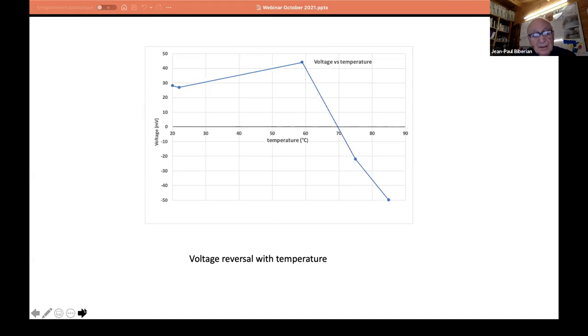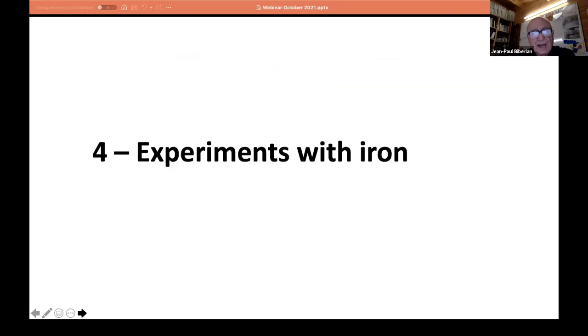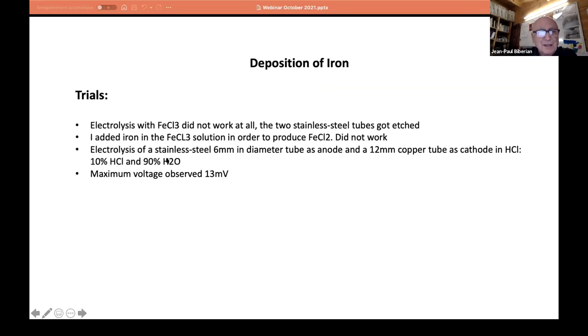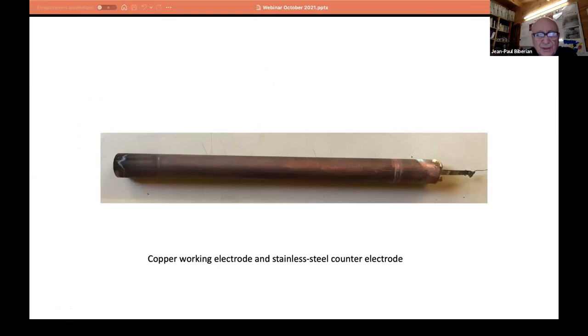Now, some people, instead of using palladium, which is very expensive, try to use iron instead. Iron can also load hydrogen, so people use iron. And I tried to deposit iron on the surface. First, I tried with FeCl3, which didn't work at all. Then I tried FeCl2, but I couldn't get anything good. I got maximum a few millivolts, but not as good as with the palladium. So I need to try to improve the deposition. But it didn't really work.